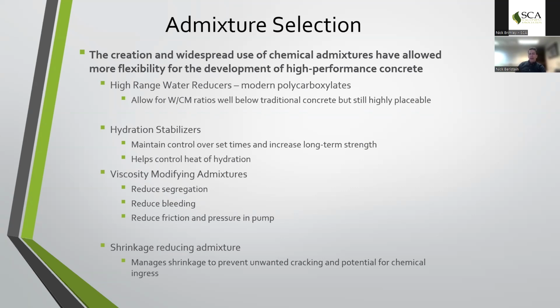And then finally, we see a fair amount of shrinkage reducing admixture requested or required for these high performance mixes. Again, in a lot of cases, it is to help eliminate or minimize the chance for cracking or ingress points within the concrete itself in the element. And so that is an admixture that we use quite often, but must be used with some care, as shrinkage reducer can have some negative impacts on your overall mix performance if used without much guidance.